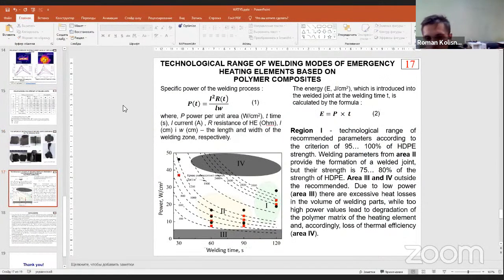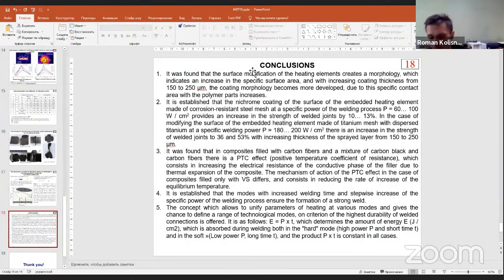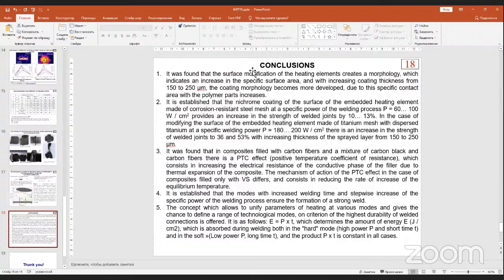So according to these results, we built a diagram which has 4 zones. In first and 2, we can form a welding joint, and in 3 and 4 there is no welding joint obtained because of lack of power or because it is excessive. So we can conclude that by modifying metal heating elements, we can obtain an increase in strength, and we found regimes that can form a welding joint with increasing strength.